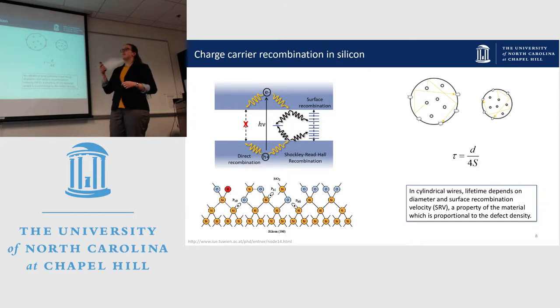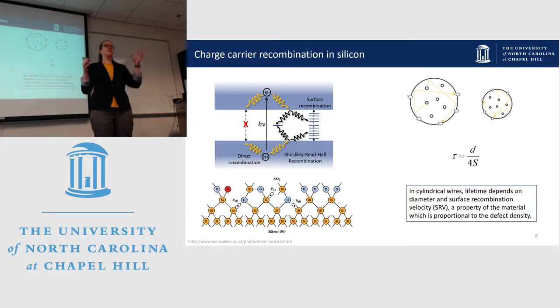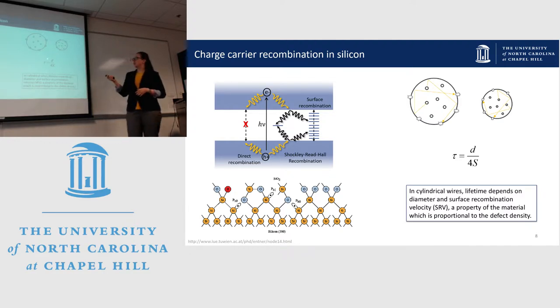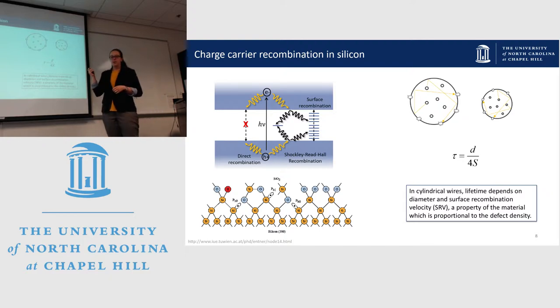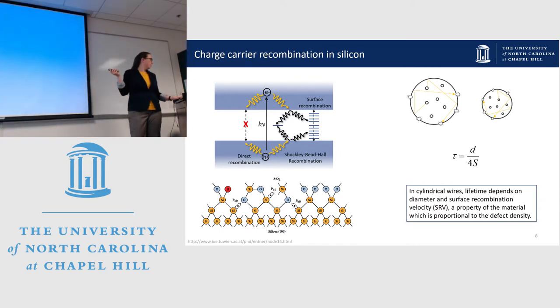What this means is that if that value of S is large, the lifetime is going to be small. Recombination is going to happen quickly. So you can relate tau, which is the lifetime, to 1 over that term S. Because these are all at the surface,